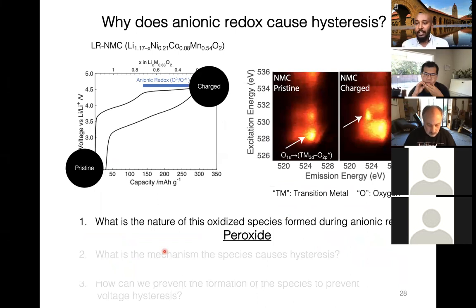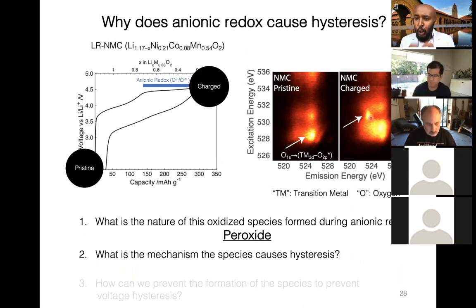So now we answer the first question. That is, the nature of the species we are observing on the RIXS map upon anionic redox is a peroxide-like species with an oxygen-oxygen bond length close to 1.5 angstrom. Now we know the species that has been correlated with anionic redox and the hysteresis. The question is, why is this short covalent bonding between oxygen atoms causing the hysteresis that we commonly observe when you have anionic redox?